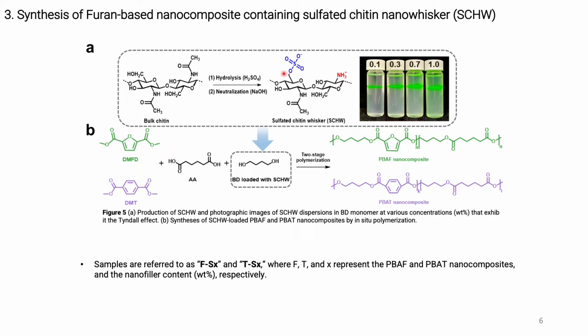The sulfated chitin nanowhiskers were produced through sulfuric acid hydrolysis of chitin, which produces a highly crystalline nanomaterial by removing amorphous regions while simultaneously converting some primary hydroxyl and acetamide groups into sulfate ester and protonated amino groups respectively, as we can see in figure 5a.